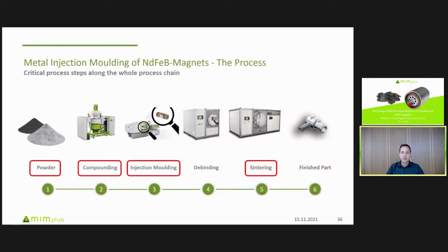That leads to challenging steps over the whole process chain, starting from the powder because it's highly reactive, coming to the compounding where you still have to work with the highly reactive powder. Then the injection molding, which is a bit special for neodymium iron boron magnets because you need an alignment system for the magnetic alignment of the part during injection molding. The debinding is not so complex, and then the thermal debinding and sintering step follows, which is a really critical step because you have to prevent the powder from reacting with light elements like carbon or oxygen. And then in the end, you have the finished part.